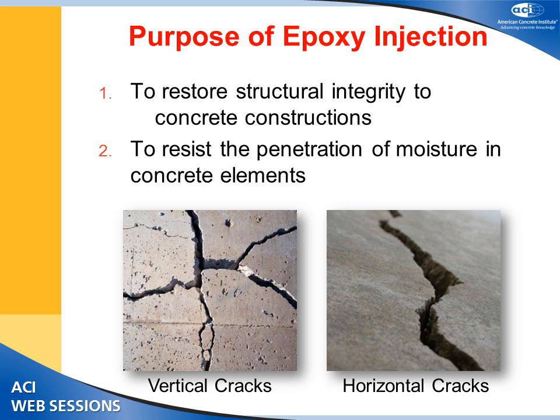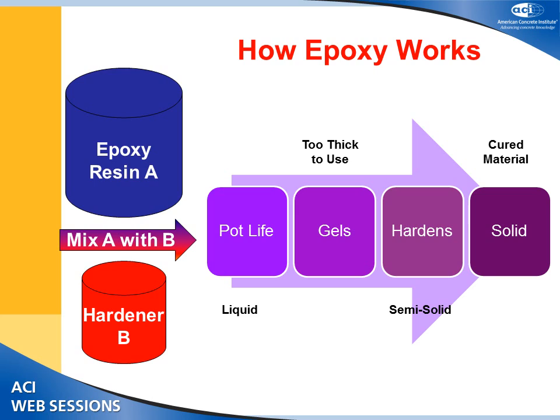When you inject epoxy into cracks in concrete, you're basically restoring the structural integrity of the cracks. Once that crack is sealed, it also helps seal the ingress of chloride and moisture into the concrete. Epoxy is typically a two-component product — A and B, resin and hardener — formulated to work at a specific mix ratio, either 1-to-1, 2-to-1, or 3-to-1.